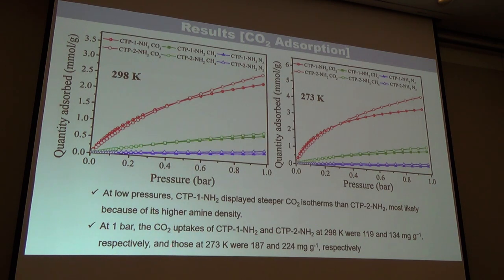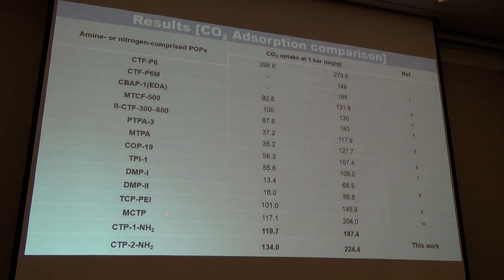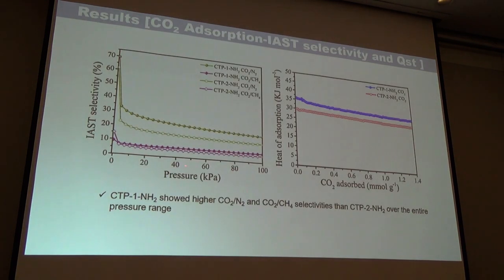The materials show high adsorption capacity at 298 as well as 273 Kelvin. As you can see, the CTP1 and CTP2 capacities are 119 and 134 at 298 Kelvin, and at 273 Kelvin it is 187 and 224 milligram per gram. Further, these results were also compared with previous reports and suggest that CTP1 shows one of the highest values obtained so far. Meanwhile, we have also calculated the IAST selectivity and the Qst value for CO2 adsorption. The IAST selectivity is calculated over nitrogen. As we can see, CTP1 shows nearly 70 and CTP2 shows nearly 60, whereas the Qst value for CO2 adsorption for the CTP1 material is nearly 35, and for CTP2 it is nearly 30.